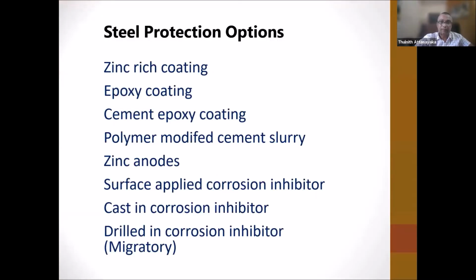Steel protection options: we are thinking zinc-rich coatings, we can have epoxy coatings, but we make sure that if you are using zinc-rich coating or epoxy coating, those coatings have to be compatible with the repair mortar or the concrete. Because sometimes, let's say we have some epoxy coatings, those are marine grade and those are not compatible with the repair mortars or concrete.